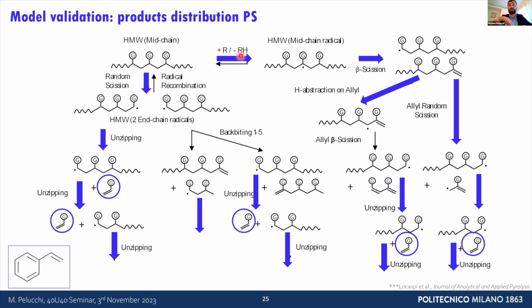If you do an H abstraction reaction, let's say you form a high molecular weight mid-chain radical, these undergo beta scission, you form an unsaturated bond on one side, and you form again this same radical that I was talking about before on the radical part that you're producing through beta scission. These, again, will undergo unzipping and so on. So basically, nearly all of the steps lead to unzipping phenomena, and unzipping leads to the detachment of one monomer. And this is how you get a large yield of monomers from polystyrene pyrolysis.